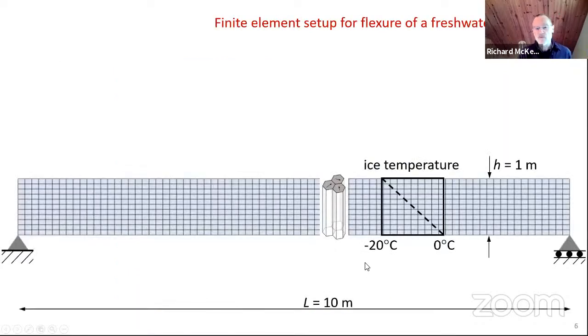The setup that we've used is the flexure of a freshwater S2 ice beam. That beam is 1 meter thick and 10 meters long. In width, we've considered a unit width, and we look at both plane stress, where it's unrestrained in the width, or plane strain conditions, where it's restrained in the width. We've got S2 ice through the thickness. We're looking at a temperature profile of -20 at the top surface, going down to 0 degrees.